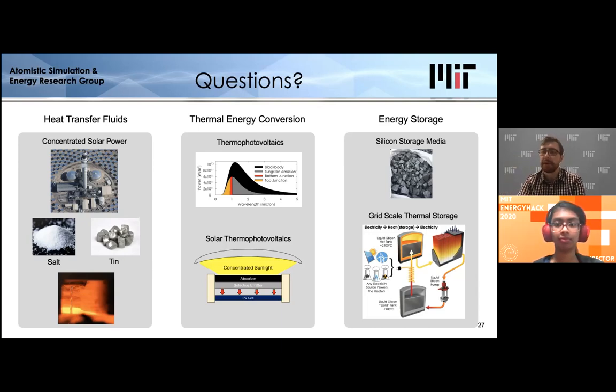So I think I answered the second part of that. Insulating things at this very high temperature is actually quite a challenge. And for those heat transfer people in the audience, basically at this temperature, radiation is the dominant mode of heat transfer. So you could have a complete vacuum gap between your thermal storage media and the outside wall, and you'd still get a huge amount of heat transfer. So the way you get around that is basically by having as much material as possible between the two surfaces. It's very interesting because it's the total opposite of what one would expect for lower temperature insulation.